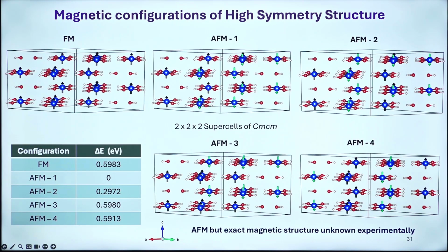Of course, we have taken Hubbard U and van der Waals because it's a layered system. We computed this, and we could see that the AFM1 structure is more favorable in terms of the total energy, which led us to proceed with the AFM1 structure.